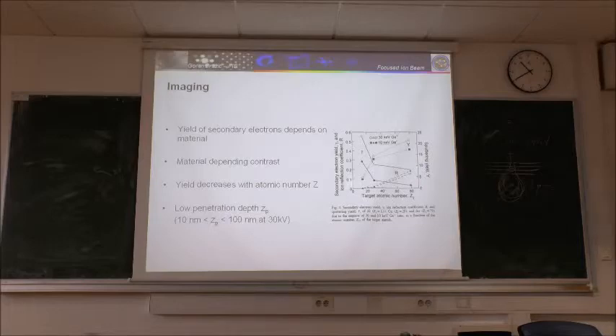Okay, now let's go to some parameters that are important for imaging. The yield of secondary electrons depends on the material. Here we have the secondary electron yield, gamma, for different energies. Let's take this one, 30 kilo electron volts. We see that the yield is lowering when the atomic number is increasing. So for low Z material, oxygen, carbon, and so on, there will be a much higher production of secondary electrons than for high Z material. This is good information. Why? Because we can most probably easily see an oxide layer on some grain boundaries. We'll see the example later on.